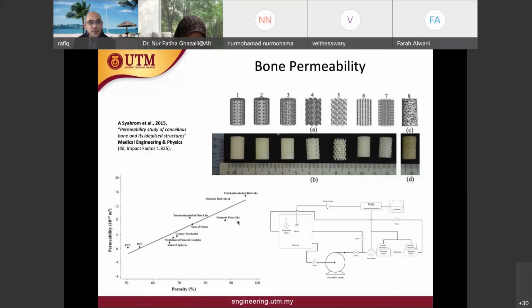And then we compare again in permeability studies. This is a permeability study of cancellous bone and its idealized structures. So we compare between prismatic plate-like, prismatic rod, tetrakaidecahedral rod, with the actual cancellous bone from the neck of femur, from the greater trochanter. You know that because cancellous bone density, porosity and structure vary across skeletal sites. So the one that you take from the spine, for example, is different from the cancellous bone that you have in the greater trochanter of the femur. So this is an extensive study by Dr. A Syahrom, who is currently the director for Meditech.